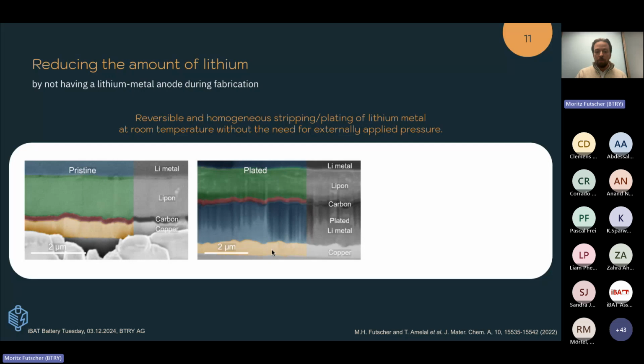And you can see this is very homogeneous by looking, for example, at the features on the bottom of the copper. They're all still present on top. So there's a really homogeneous growth. And this is done at room temperature and without applying any pressure.